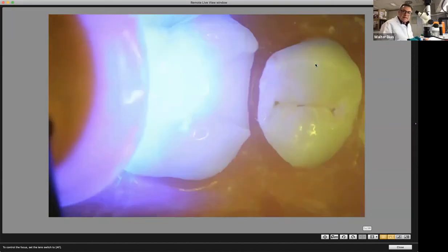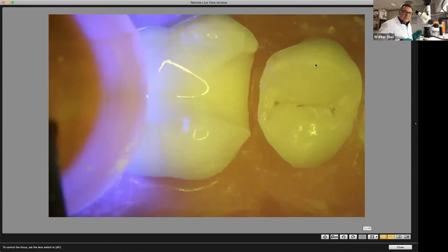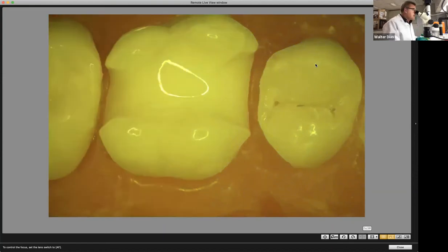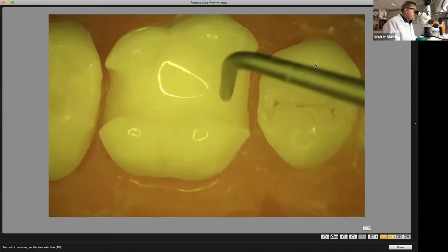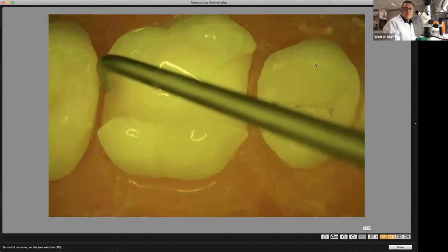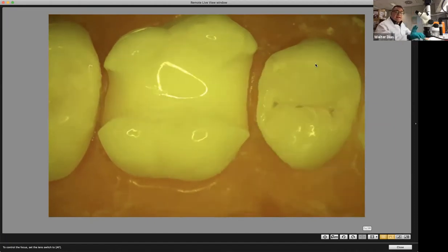And if you want to tack cure this, this is the most beautiful thing. You do 1 second here, 1 second there, and tack cure this so it's stable. Okay, look at this. It's stable, but it's not cured inside, and you just let it self-cure. So doing like that, you're going to have much less shrinkage stress, much less sensitivity. Don't forget to do these things. Let us know in the future if you had problems with sensitivity and if this helped you.